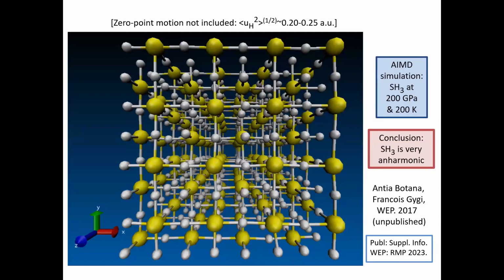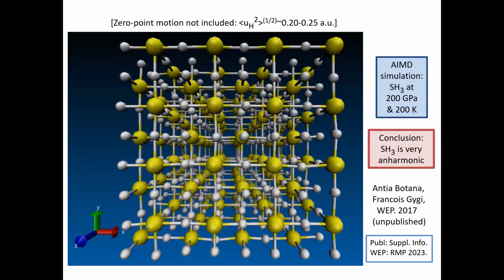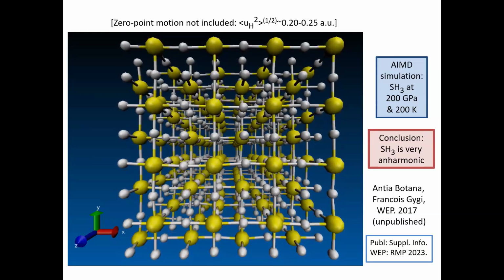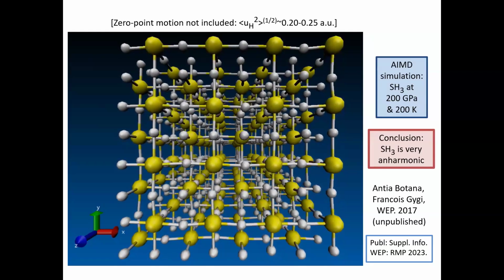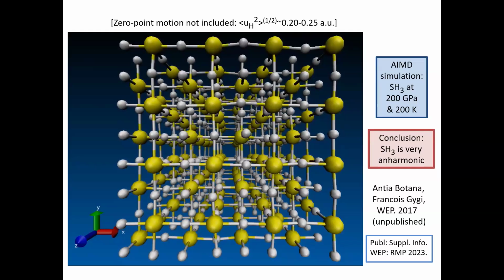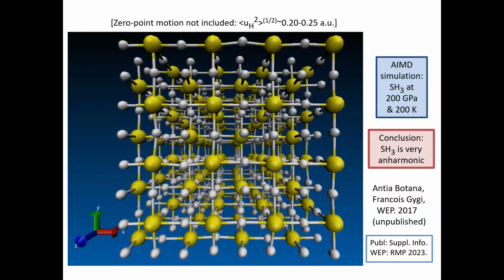Okay, just to show this. What is a little bit special, or more than a little bit special, about hydrogen is that if you just use quantum mechanics to calculate forces on the ions, hydrogen, proton, and the ion sulfur in this case, and just do time step by time step updating of positions and velocities and so forth, and conserve energy, then you get what's called molecular dynamics. And what you can see here is a sulfur with the atomic weight of 32 is hardly moving. And that's what you normally see in these calculations. But what you see is the hydrogens are jumping all around. That's just the reflection that they are such light materials. Their atomic weight is 1. It's the lightest possible of any nucleus.